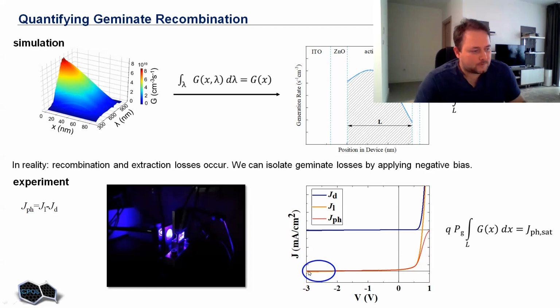So by applying a large reverse bias, we create conditions where we can neglect non-geminate recombination. That means the measured saturated photocurrent at large reverse bias should be equal to the total amount of excitons generated in the active layer per second times some coefficient P_G, which stands for the geminate recombination prefactor. This geminate recombination prefactor shows what part of the photo-generated excitons actually made it to the interface and were split into free electrons and holes.